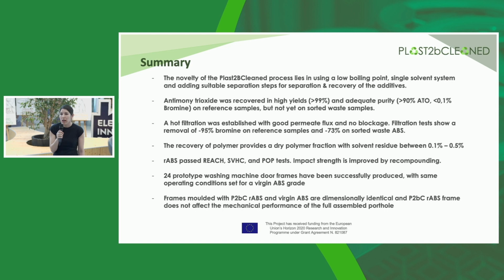Recovered polymer was of very low solvent residue, typically around 0.1%, and recycled ABS passed all performed REACH, SVHC and POP tests, and only impact strength needed to be improved in recompounding, which was achieved at the end and allowed production of 24 prototypes of washing machine door frames that were successfully produced and tested in operating conditions and compared to virgin ABS grade. And as already mentioned, no effects on the mechanical performance of these prototypes have been observed. So with this, we finished this section. So maybe if there are any questions.